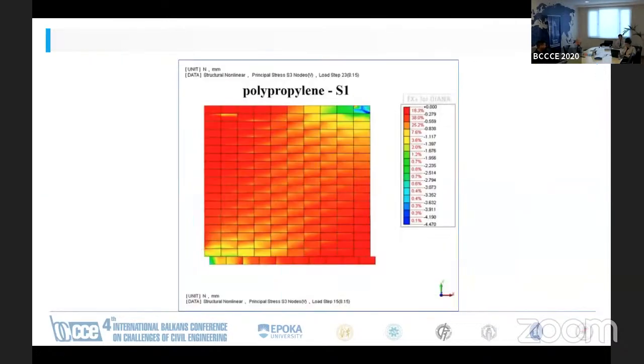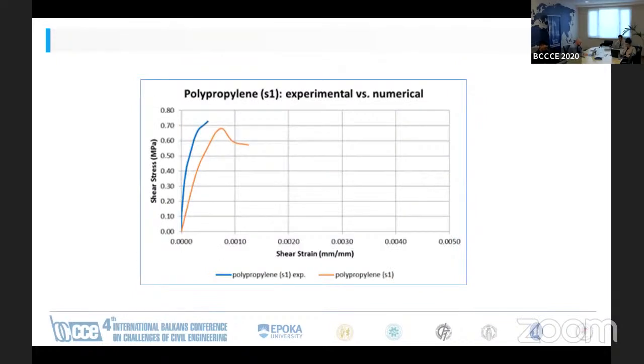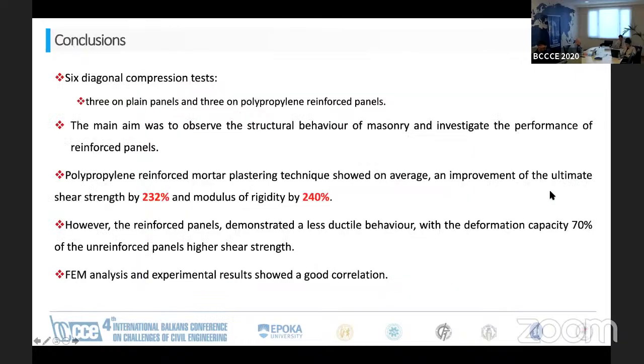And we somehow tried to simulate what actually happened in the test results. And you could see here the distribution of the stresses along the compressed diagonal. We also tried to calculate the shear stress and shear strain for both cases, for the experimental result and for the numerical result. As you can see, it is a pretty good fit, but with the numerical results being a little bit more ductile than the actual ones.